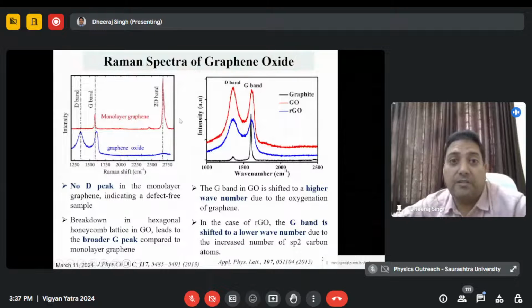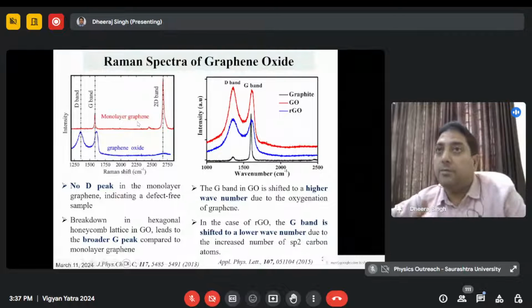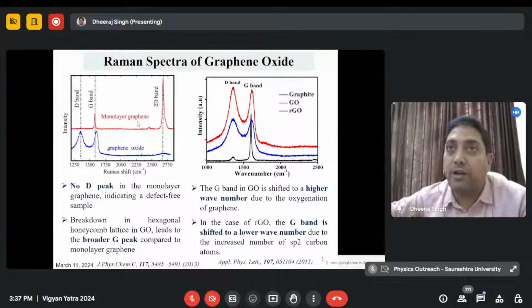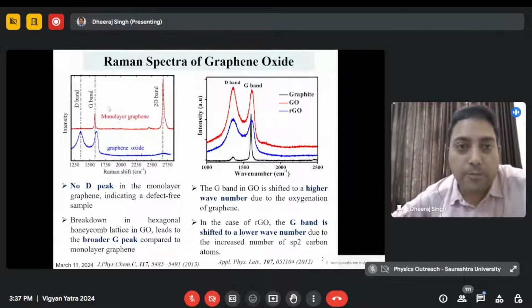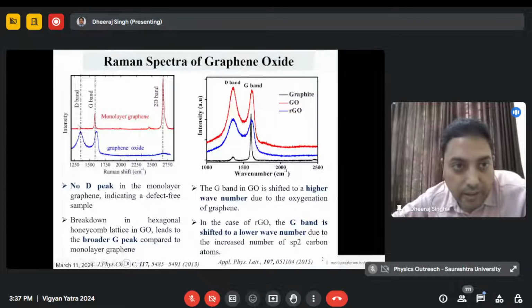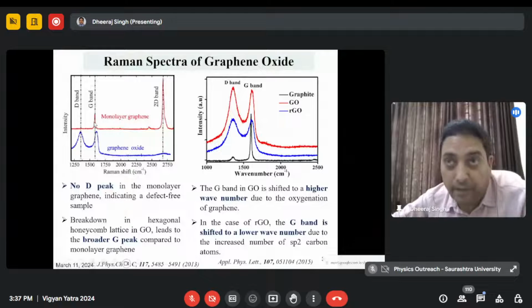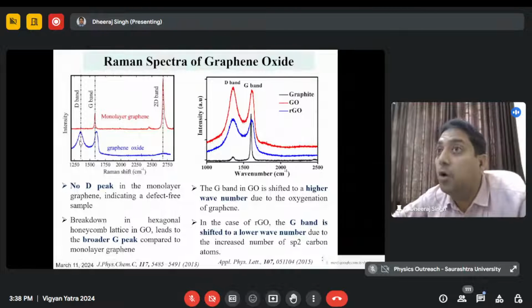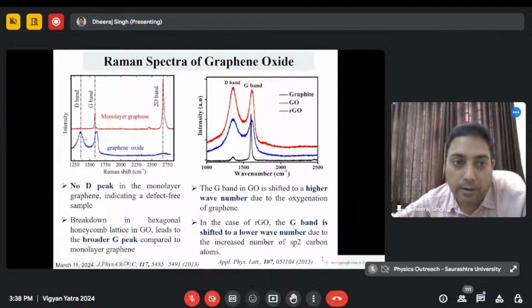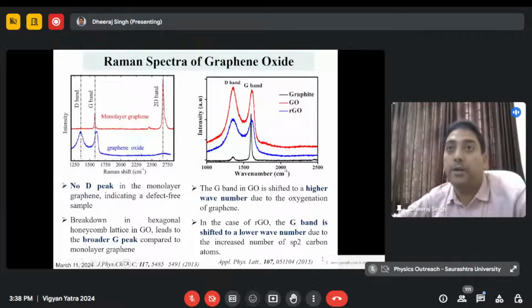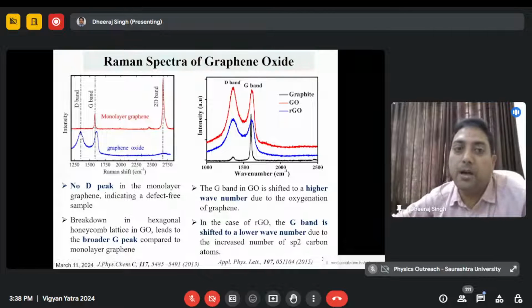Now you can see the Raman spectra of graphene oxide. Suppose this is the monolayer graphene, and now graphene oxide, which means we have deliberately made an oxidation in your graphene sample. So how can Raman spectroscopy ideally detect these changes? You can see that in pure monolayer graphene only the G band, the in-plane vibration peak, is observed. But when you have made an oxidation in your sample, we call it graphene oxide. Now any deviation from the honeycomb lattice means a disorder or D peak will be introduced. A new peak is generated at almost 1350 centimeter inverse. The appearance of this new peak is a clear identification of the D peak or graphene oxide.